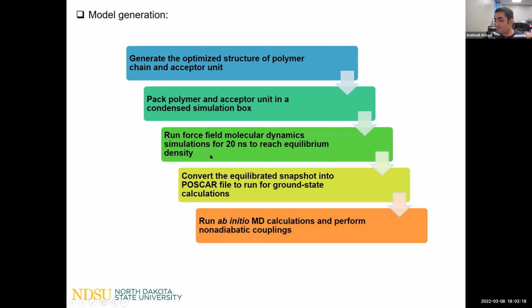So how I performed temperature and pressure, yeah, that was around 20 nanoseconds. I used multiple isobaric and isochoric, if I'm pronouncing them right, ensembles. Yes, at the end, I ran under NPT ensemble. I let it go to the equilibrium situation, at the beginning, under huge pressure and temperature with annealing, then cooling down and getting rid of the pressure and temperature. But at the end, that was relaxed under the atmosphere pressure and reached the room temperature.